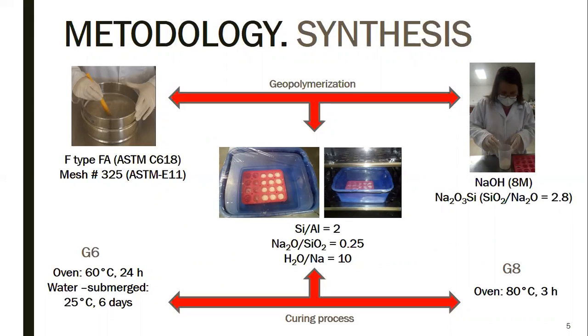The geopolymer slurry was cast into plastic molds and subjected to a hydrothermal curing process. One of them was labeled as G6 and it was performed in an oven at 60 Celsius degrees for a period of 24 hours, followed by a water submerged curing process at 25 Celsius degrees for 6 days. The second curing process was labeled as G8 and it was performed in an oven at 80 Celsius degrees for a period of 3 hours.